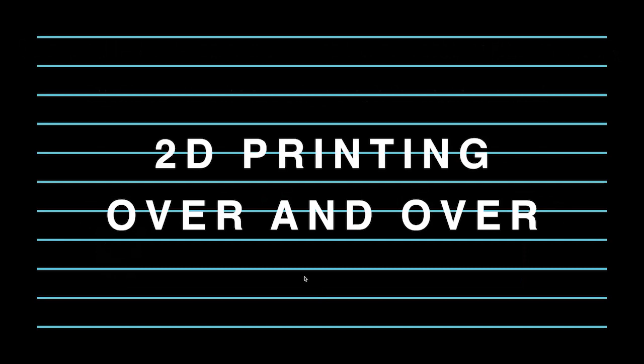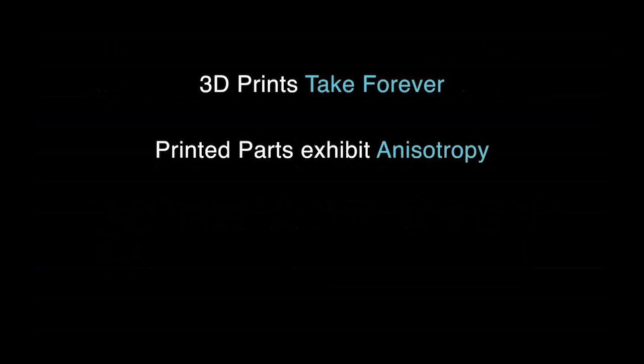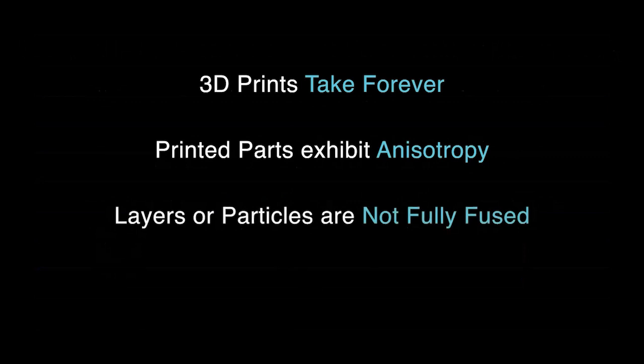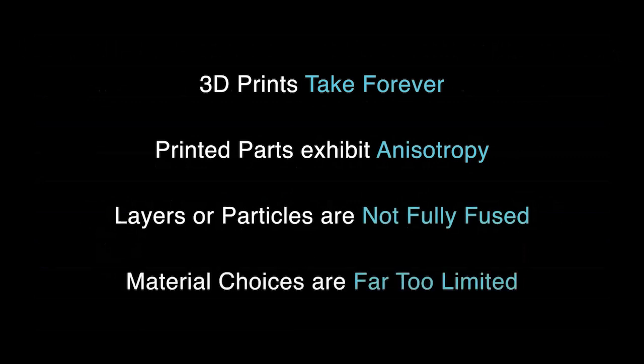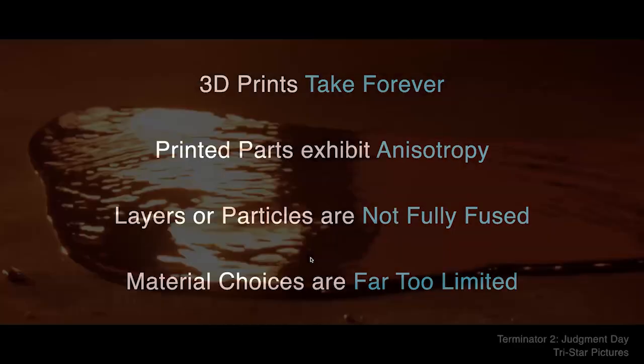I think all of these processes are more akin to 2D printing over and over and over again, rather than 3D printing. And I think 3D printing is a slow process traditionally because of the layer by layer approaches that lead to anisotropy. Because of the particles or layers that are not fully fused, it results in that anisotropy. And the material choices, especially for light-based polymerizations, have been far too limited.